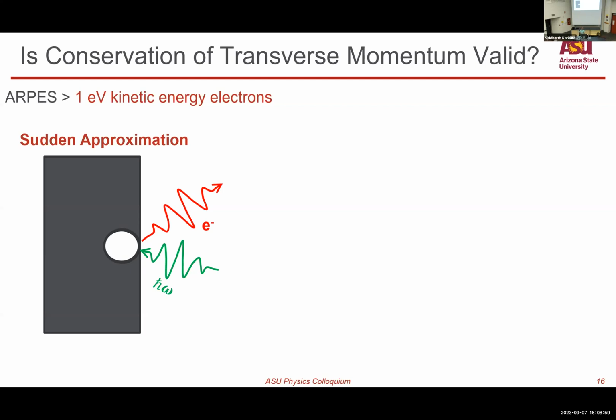So we know experimentally it's true in this regime. However, in fact, all of our photoemission theories have a very subtle approximation built into them. They call it the sudden approximation, which says when a photon excites an electron and it is emitted, it instantly stops interacting with the n-1 excited state surface that it has left behind. And experimentally in ARPES techniques, they have found the sudden approximation to be true. No one has ever seen it being violated so far.